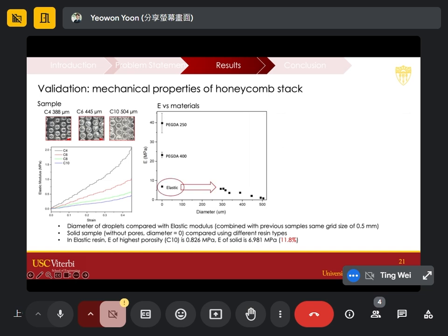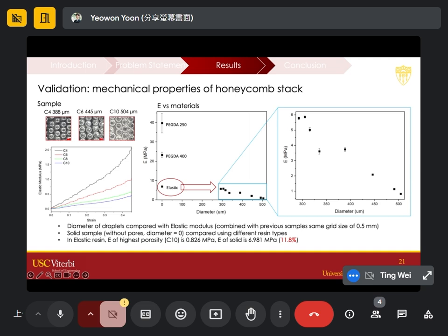this is the elastic resin without any pores, having about 8 megapascal. And all these variations are achieved with the same resin, but putting in different diameters of droplets inside. So a larger droplet ends up in a lower elastic modulus, where with the maximum droplet size of C10, we're able to achieve about 11.8% of the bulk modulus.